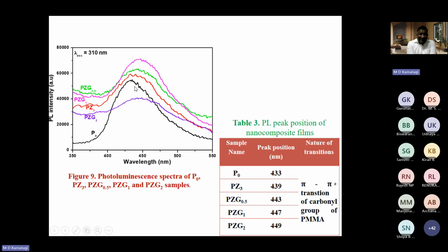But when we compare with the P0 sample or PZ3, this is the red. The photoluminescence intensity of PZG1 has increased significantly. So this shows that doping should be done wisely. So merely increasing the dopants will not increase the properties. There has to be a calculation in the percentage of the dopants.